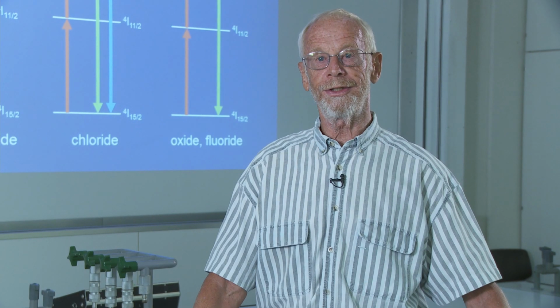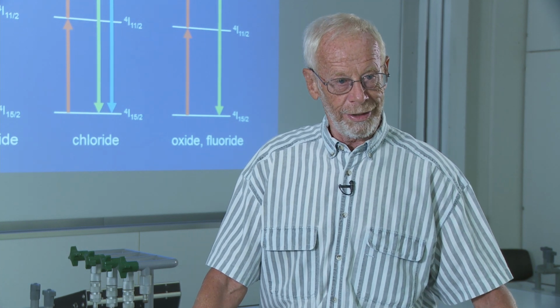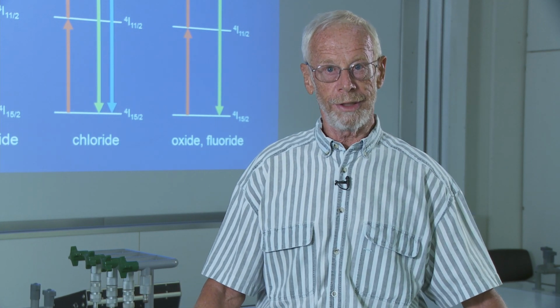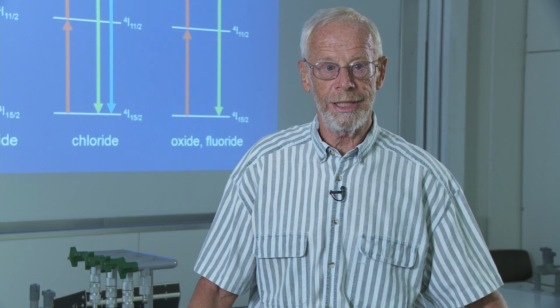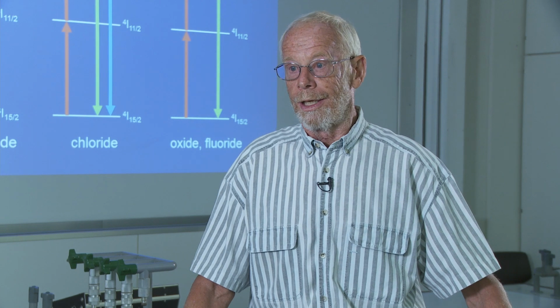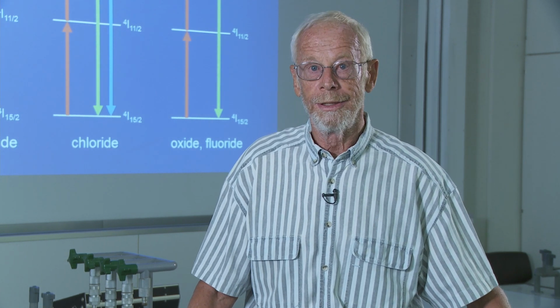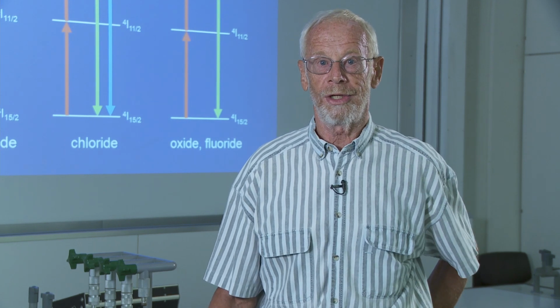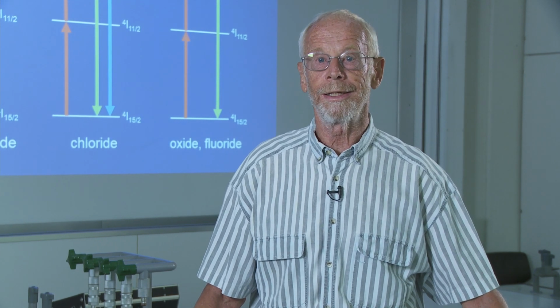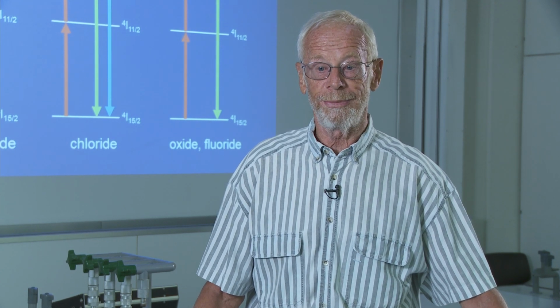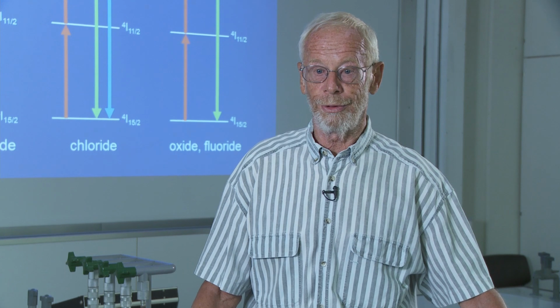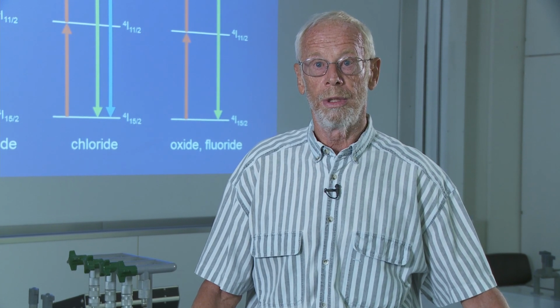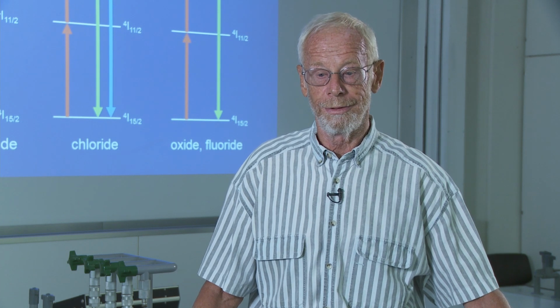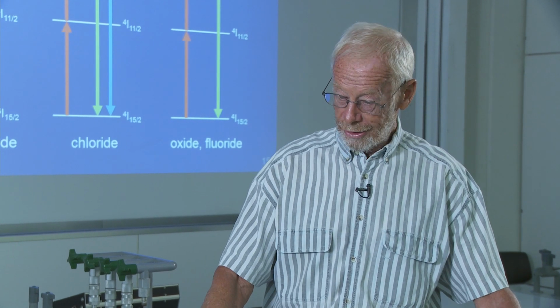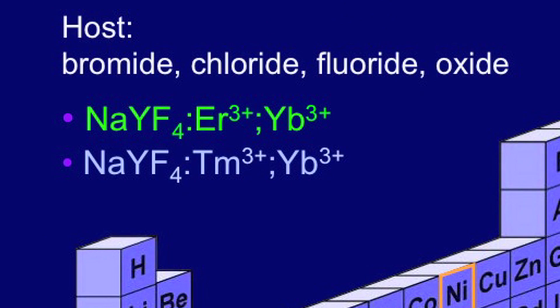So, scientifically, this was very neat. We are able to rationally tune the emission color by chemical variation. However, as an attempt to make a useful material, it was a failure. We tried very hard in the early 1990s to make a blue laser based on this principle, but we had to realize that these materials were simply too hygroscopic for such an application. So we grudgingly returned to the mainstream, so to speak, to the fluorides.